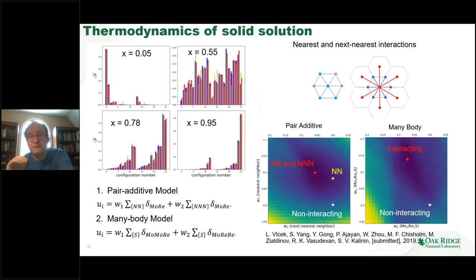And notice what it means. It means that I've taken a set of observations of the system at very different levels of doping. This data has a lot of information in terms of the atomic configurations. I was able to take this data and compress it to just two numbers that determine the interaction between the rhenium atoms. I built the generative physical model. And based on this model, I can do everything. I can reconstruct the phase diagram. I can reconstruct any number of representations of microstructure in the intermediate concentrations.